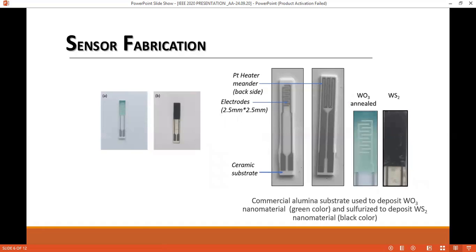Here is the picture of the commercial alumina substrate used and the fabricated sensor. The substrate comprises interdigitated electrodes on the front side and a platinum resistive heater meander on the back side. The heater meander is characterized to set the operating temperature of the fabricated sensor by applying an external power supply.